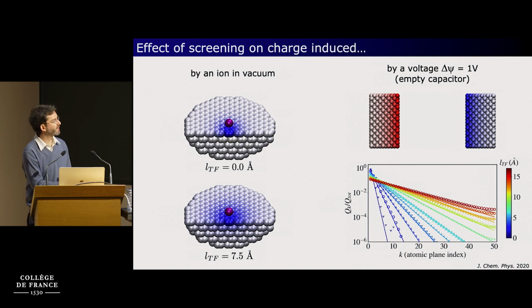If you increase the Thomas Fermi length from the perfect metal case to a finite value, then the charge distribution spreads both laterally and also as you go deeper and deeper into the electrode. And this decay inside the electrode, you can see better here for the charge induced in an empty capacitor when you apply a voltage. So the bottom panel here represents the average charge, or the charge of each atomic plane, as you go further into the electrode for various values of the screening length. And so the charge indeed decays with this model exponentially with decay length, which is the expected Thomas Fermi screening length.